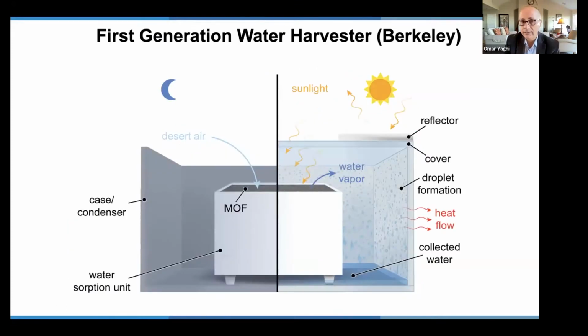So we designed a prototype to show that this works in the desert. This is a prototype with a box within a box. And the MOF is in this smaller box. Water from desert air goes into the MOF. And then during the day, you close the outside box. The inside heats up as you expose it to sunlight. Water comes out and condenses on the walls of the box, and you can collect water.